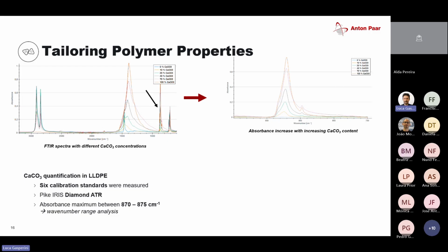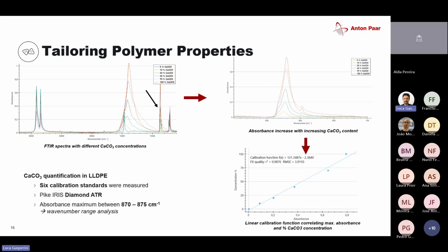So ideally, you find a peak which behaves like this, and what you do with the software now is that you tell the software, please find the highest peak within this spectral range. So from, like, this is 900 and 800, for example, and then the instrument will fully automatically mark the peaks, and then you will get a linear regression model like this. So next time when you measure a sample, what will happen? The instrument will actually measure the peak height in this specific area, and from the peak height, from the absorbance, we can actually calculate the concentration.